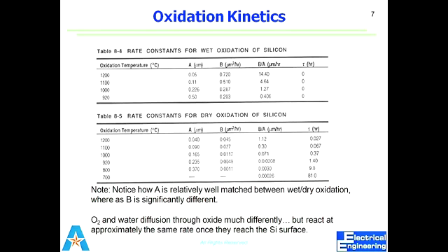So what they actually do: if I have 1000 nanometer, meaning 1 micron, first 200 nanometer, or first 100 nanometer, would be dry oxidation, just to have a better quality, to have a better isolation. Then I quickly do wet oxidation and grow up to 950, and the last 50 again dry oxidation. So this is what they do.